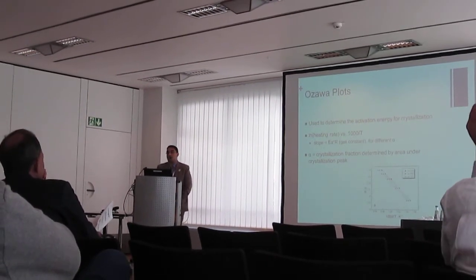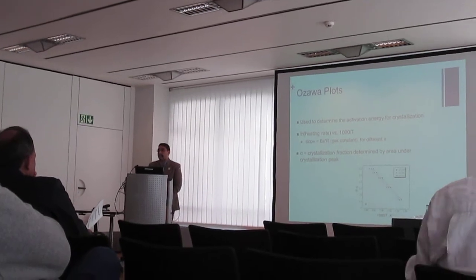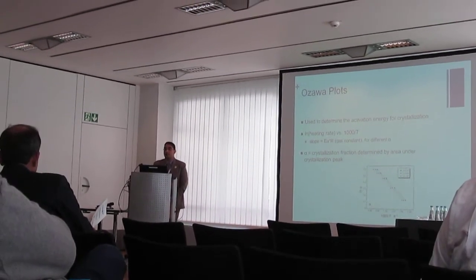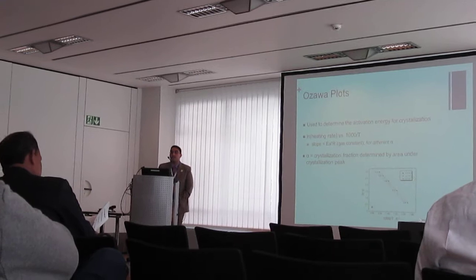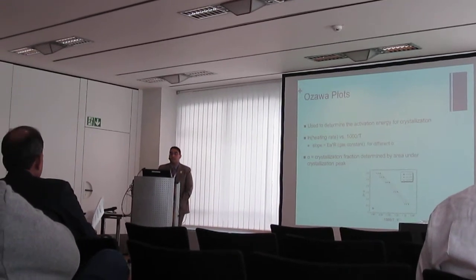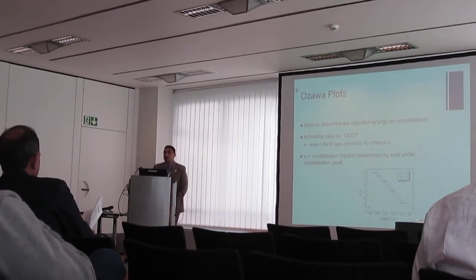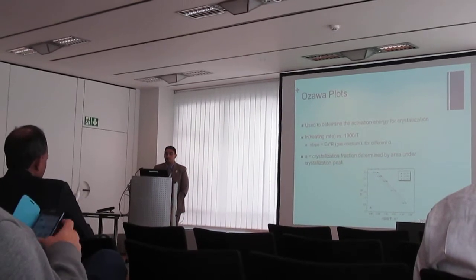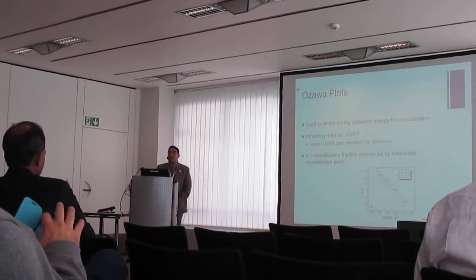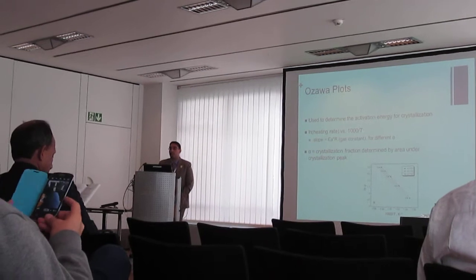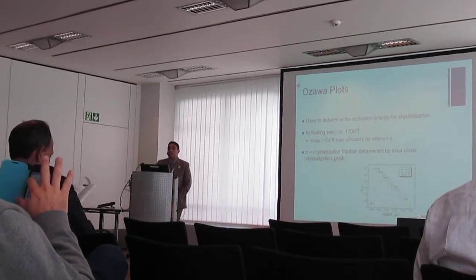To determine the crystallization kinetics, we first need to find the activation energy of crystallization. Our group did this by creating Ozawa plots for the different particle sizes and the different bioglass. The Ozawa plot relates the log of the heating rate versus 1,000 over temperature.